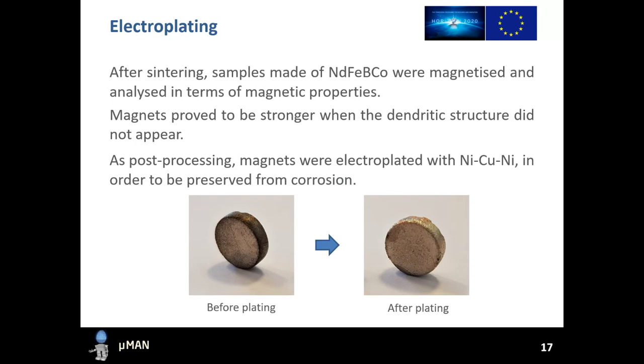After sintering, samples made of neodymium, iron, boron, and cobalt were magnetized and analyzed in terms of magnetic properties. Magnets proved to be stronger when the dendritic structure did not appear. As post-processing, magnets were electroplated with nickel, copper, and nickel in order to be preserved from corrosion.